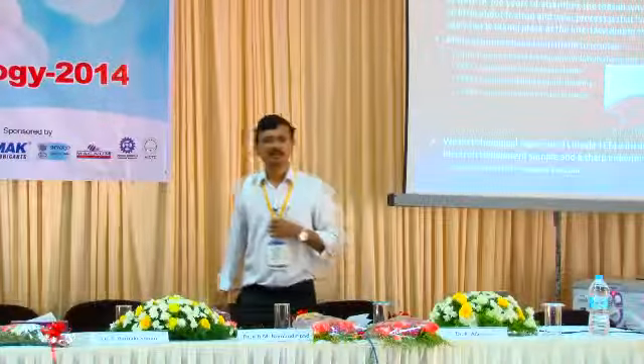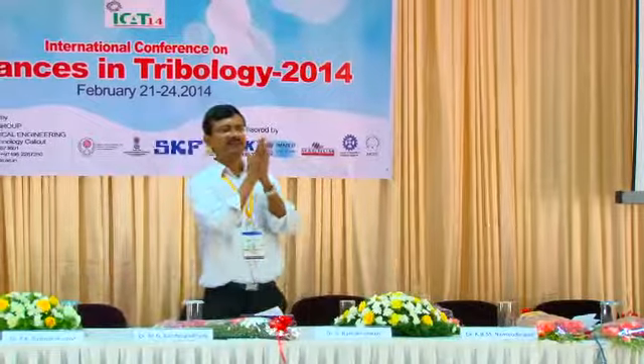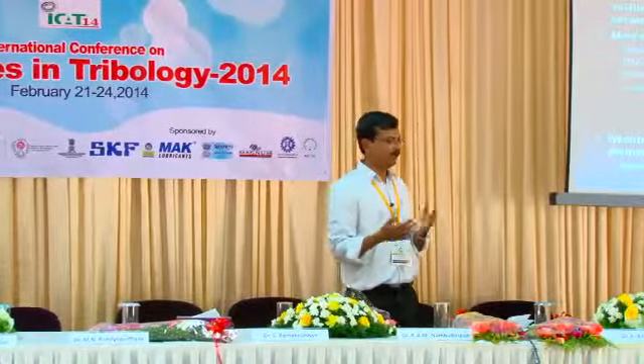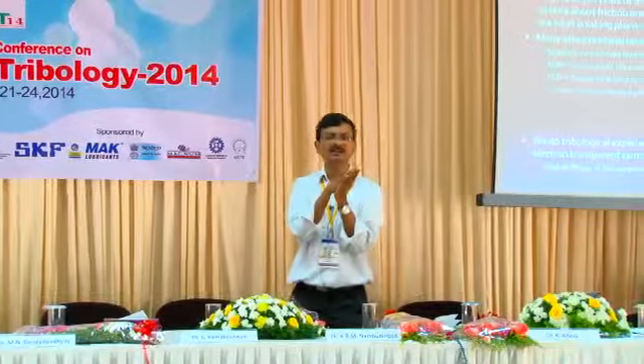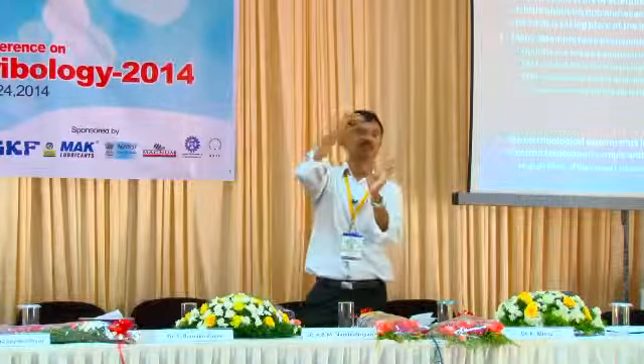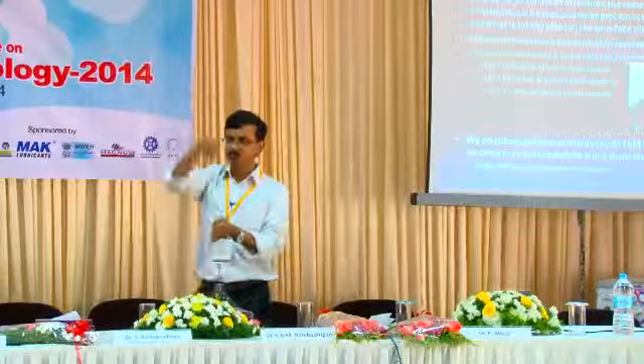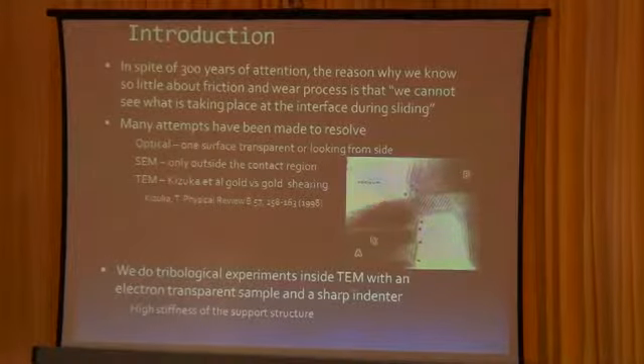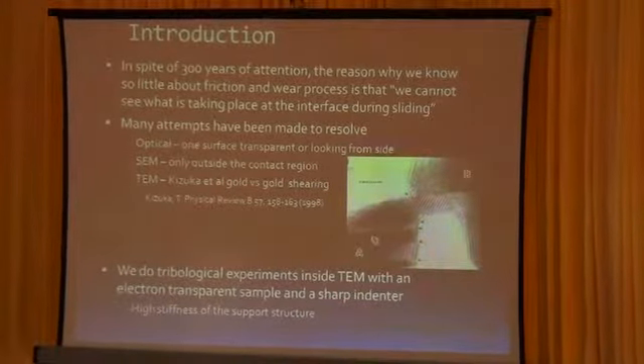Okay, that brings me to why we want to do this experiment in TEM. One of the main problems in tribology is that we cannot see what is happening at the interface. When two surfaces are rubbing, it's not visible. So people have made many attempts, by making one thing transparent and observing with an optical microscope. And there are people who are trying to look from the side using scanning electron microscope. But in transmission electron microscope, since the electrons are transmitting through the material, we will be able to observe both the side surface as well as the subsurface simultaneously and see what is happening. Seeing is believing. So we do this experiment.